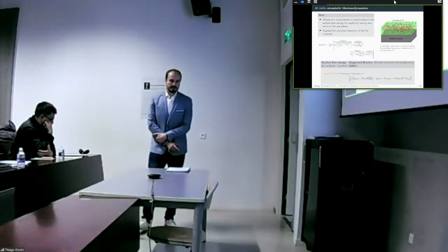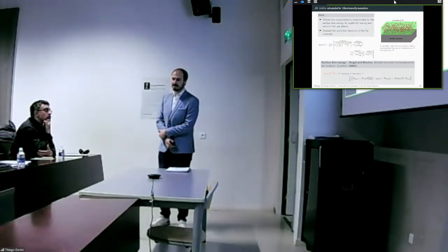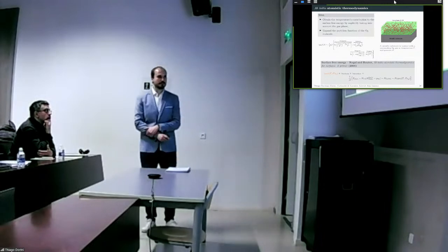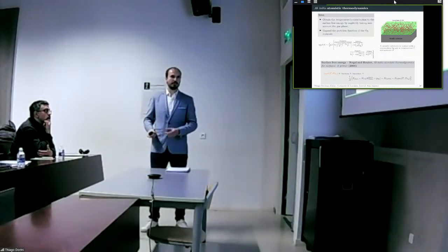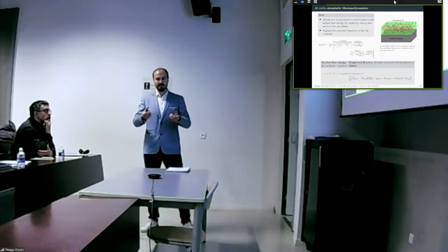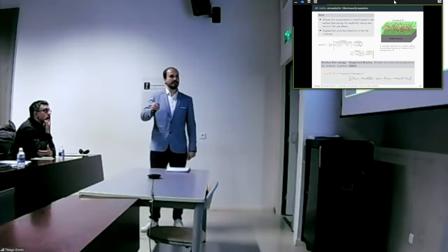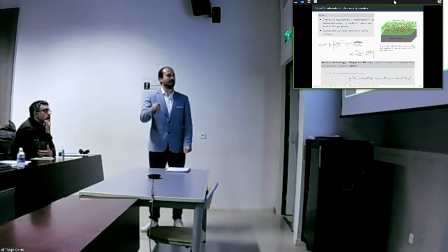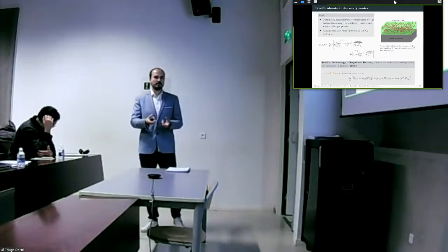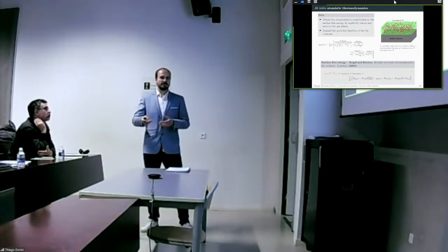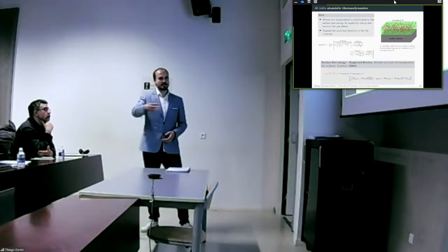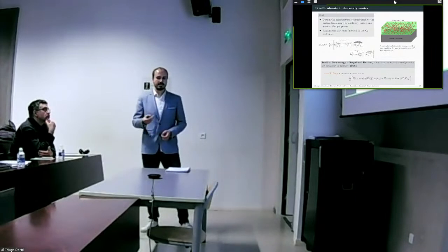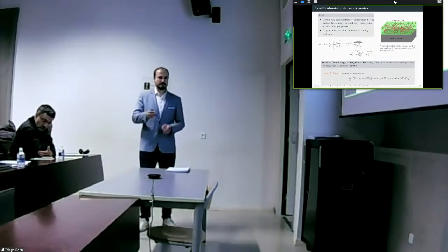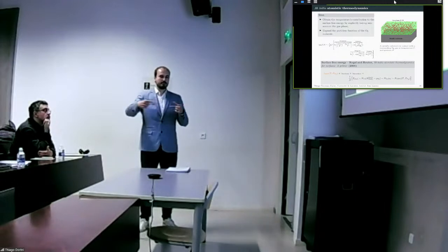Can you comment on it? Yes, it's a real limitation of USPEX, because in our case, you fix the substrate. We have chosen only 3, so we have this constraint that you only add on this surface region, which is a small region. But we try to compensate for this by changing the composition considerably. So in our case, I think we have a very good range of structures in the configurational space.